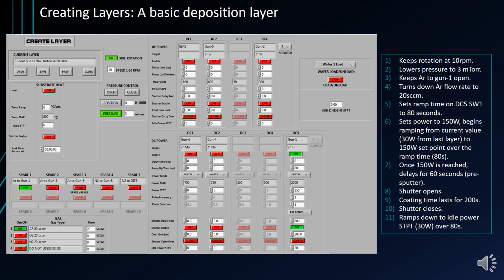The next layer we'll create will jump off where we just ended the last layer. This is our deposition layer. I've stepped the pressure down to 3 millitorr, which is very appropriate for sputtering at reasonable rates. I've also turned down the flow rate to 20 SCCM. The combination of 20 SCCM and 3 millitorr is a convention I intend to stick with for the purpose of consistency across various general processes. You can of course deviate from this.